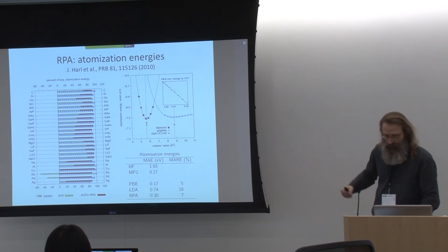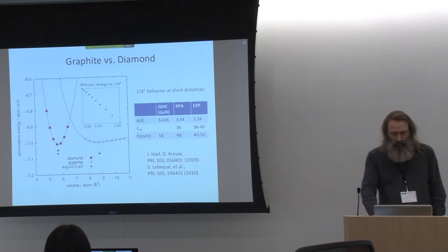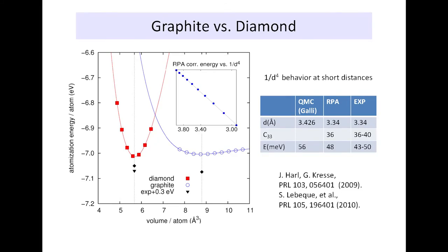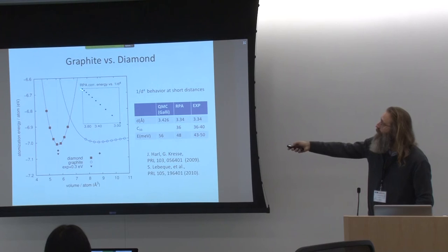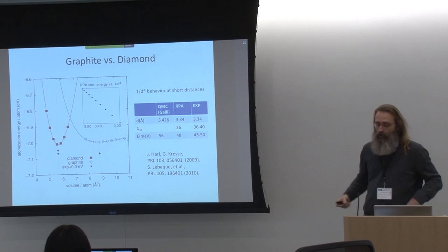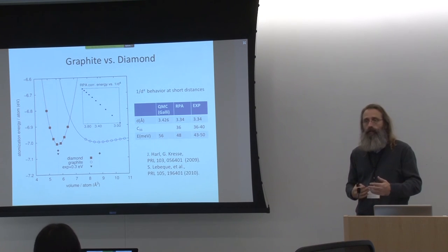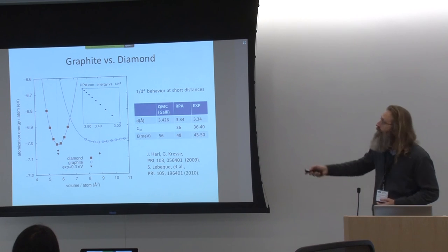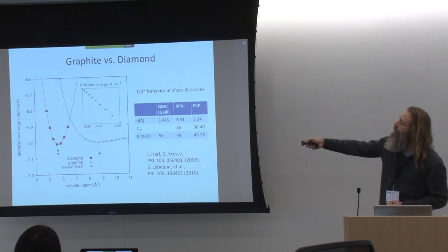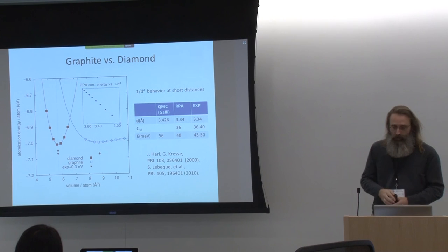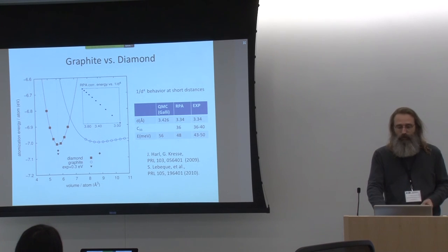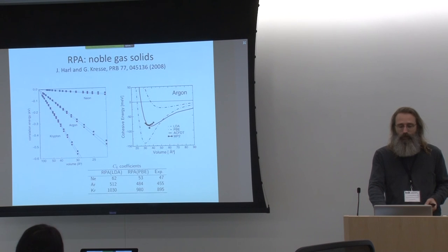Yes. So if we then go to, okay, that is sort of making this point again. Another thing is that the behavior of the total energy with respect to the interlayer distance in graphite has the right character. So it should behave as 1 over the interlayer distance to the power 4, that we do get out of our random phase approximation calculations for the total energy.